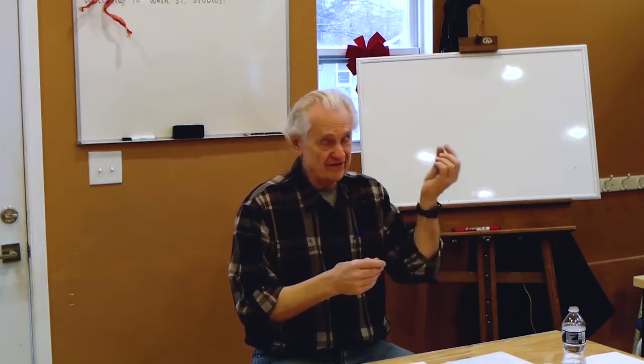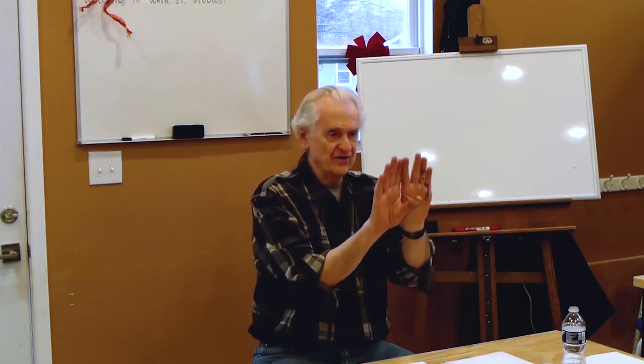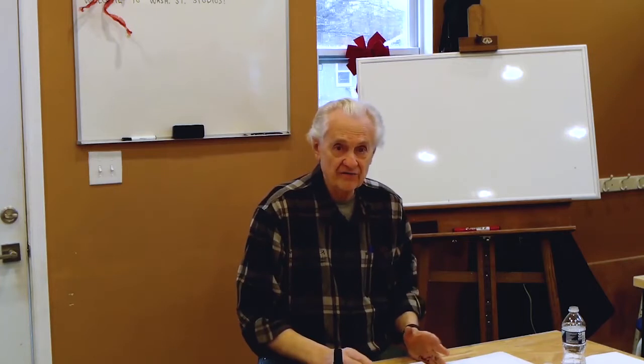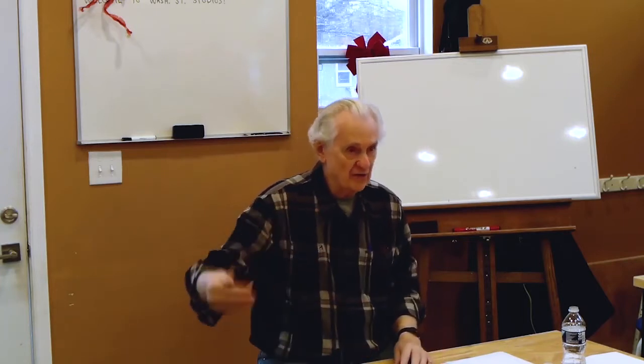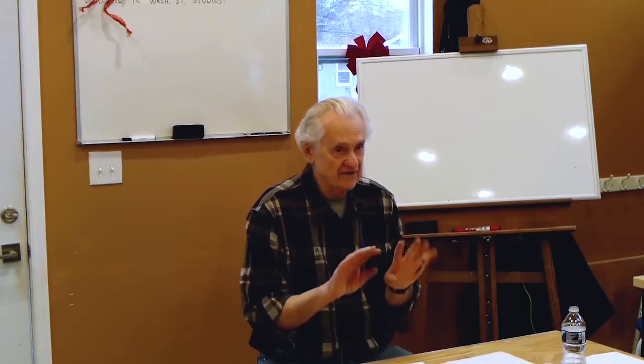So when you're rolling out a slab, a quarter of an inch or whatever you're rolling out, when you get to the edges, the slab is actually sort of tearing, if you want to think about it. You can't see it. But because the slab is doing this as it expands, this is tension. So it actually is weak. That's the reason why, if you're cutting parts out of a slab, you want to stay away from the very edge of the slab. You can't avoid the tension on the edge.